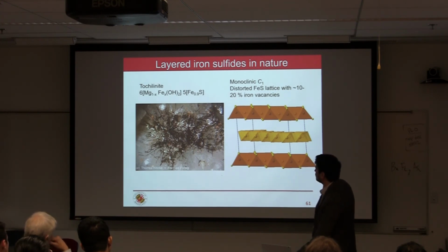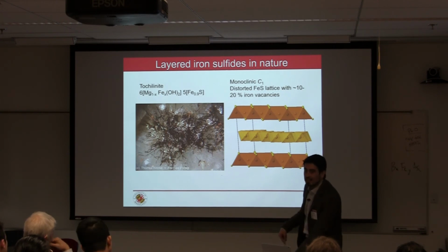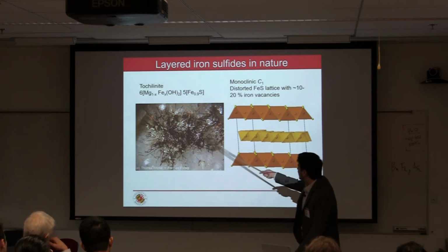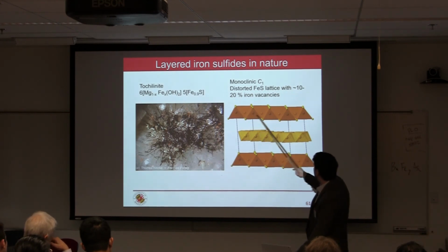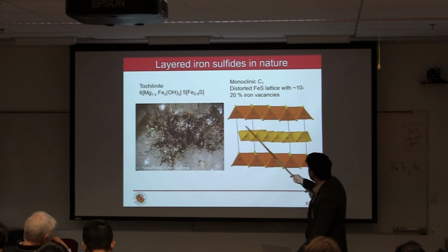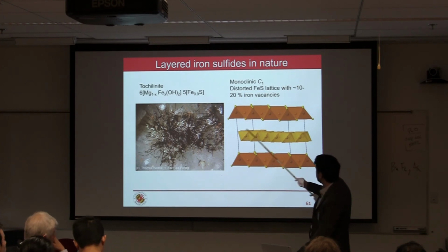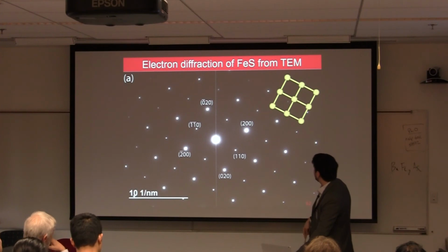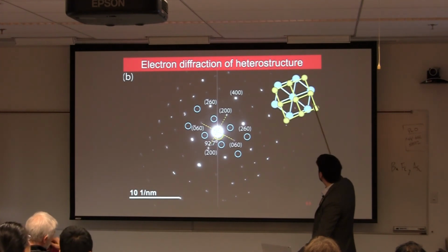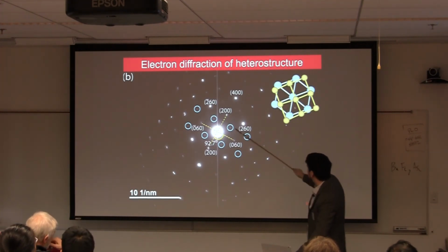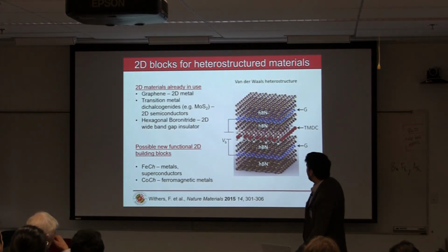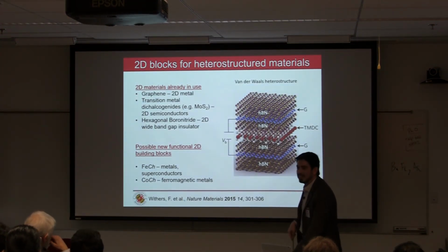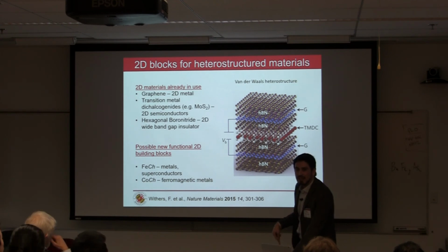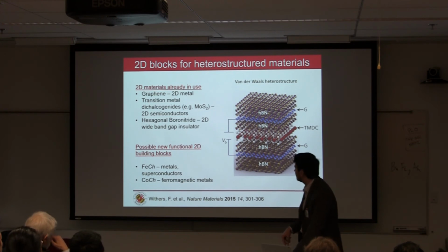Just because we're actually doing something that nature already does, lo and behold, we're able to make some new phases that nature had sort of made already, which is to make these iron sulfide square lattices intercalated by hexagonal brucite-type hydroxides like this. This is just an electron diffraction pattern of the square lattice that we're after, and then a hexagonal lattice that interleaves between the two as well, as you can see from the satellite reflections. Dave Mandrus talked about making heterostructures like Legos, and so perhaps we could make, through hydrothermal techniques as well, heterostructures of square lattices with hexagonal-based ones.